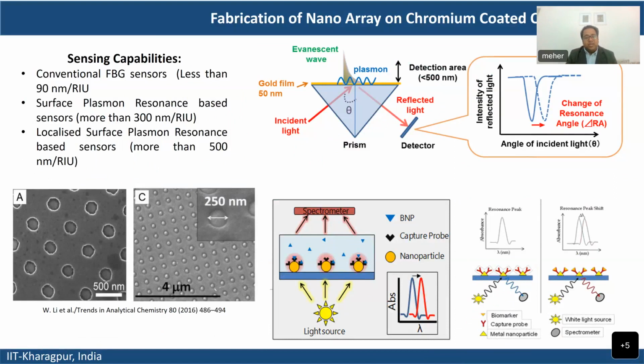But there are other sensors also which evolved in the meantime. So there are surface plasmon resonance based sensors, and these sensors are very good, much better than the FBG sensors. You can see the sensitivity is around 300 nanometers per RIU. And then there are the localized surface plasmon sensors, which are much better again. The sensitivity is around 500 nanometers per RIU. So sensitivity is much greater than in surface plasmon resonance based sensors.